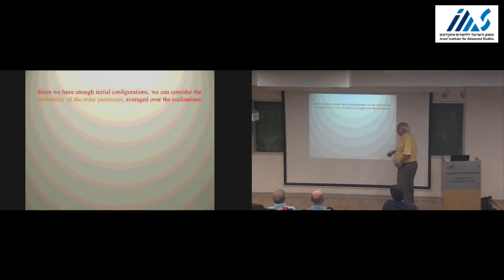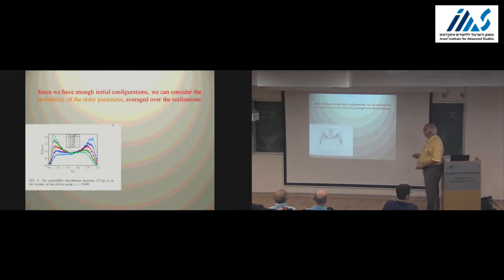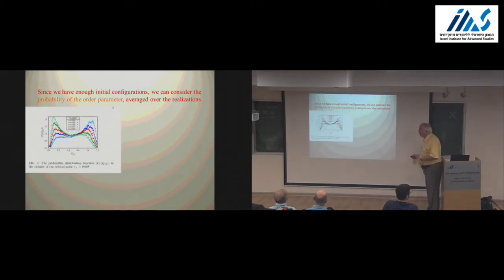But now, you see, I'm really aiming at an increase in correlation length. Now, you might tell me, wait, this is a first-order transition. So usually in a first-order transition, there is no increase in correlation length. Okay, usually. Now I want to explain why here we do. So since we have enough initial configurations, we can consider the probability to see the order parameter. Okay, because we can do things. And now we see something very interesting.